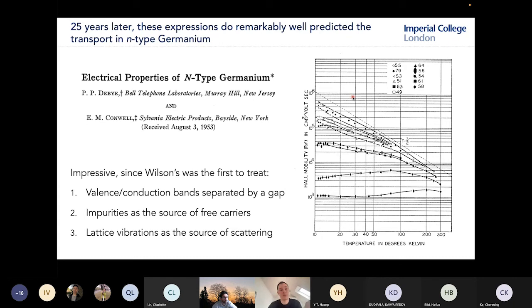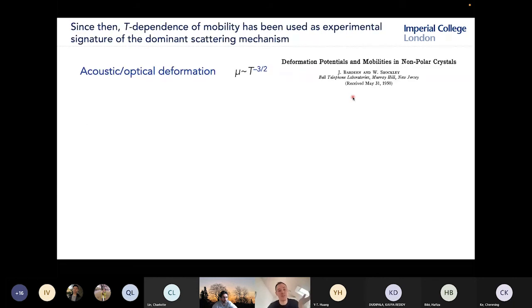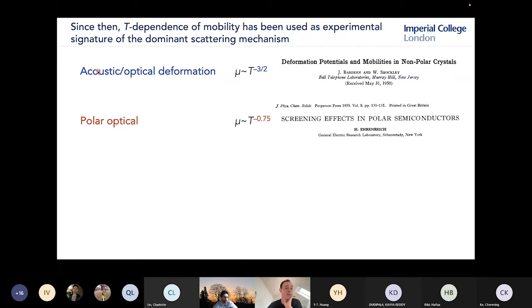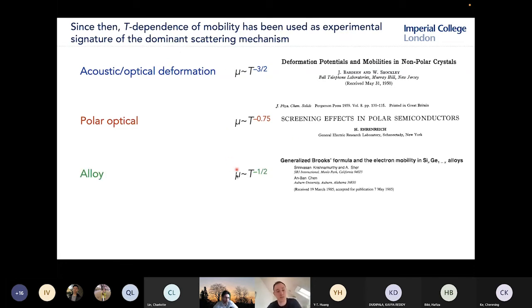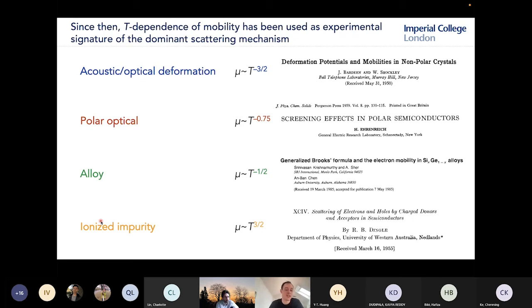Basically, since Wilson's paper, the temperature dependence of mobility has been used as a signature of the dominant scattering mechanism in materials. If you measure your mobility and you see it varies as this T⁻³ᐟ², then typically you would assume that it has optical or acoustic deformation potential scattering, which is limiting your mobility. If you see T⁻⁰·⁵, then this is considered an indication of polar optical phonon scattering. Alloy scattering has its own temperature dependence, and then impurity scattering has this positive temperature dependence. So as you increase the temperature, you expect the mobility to increase.